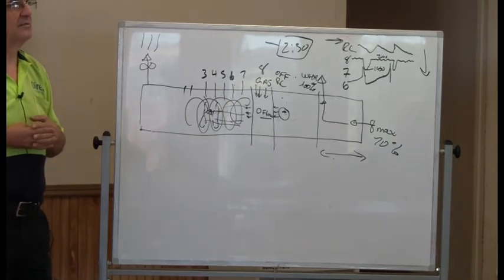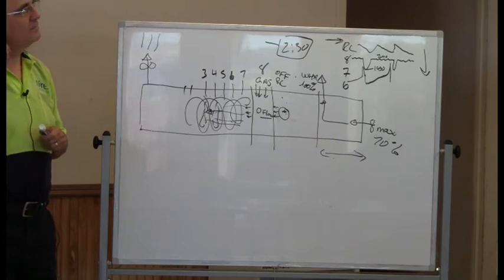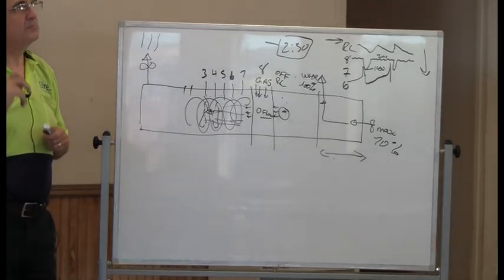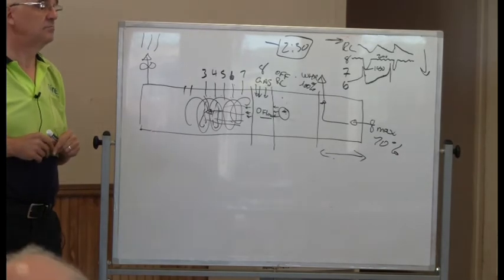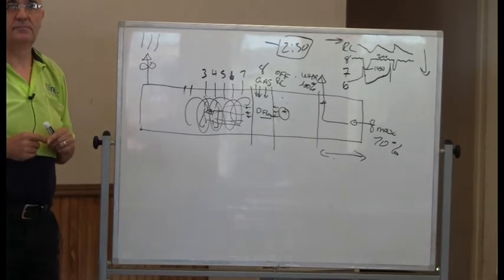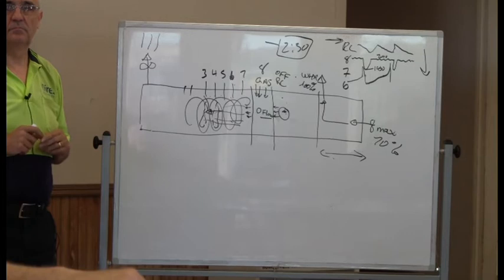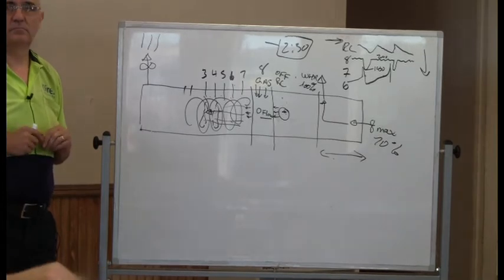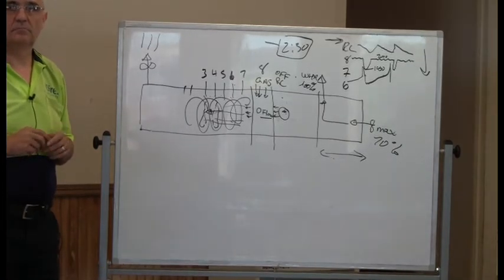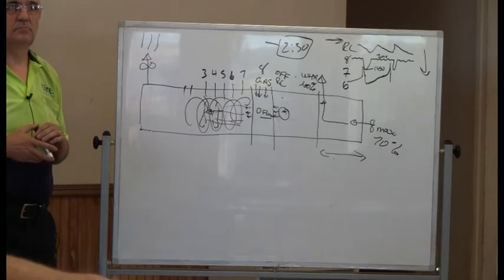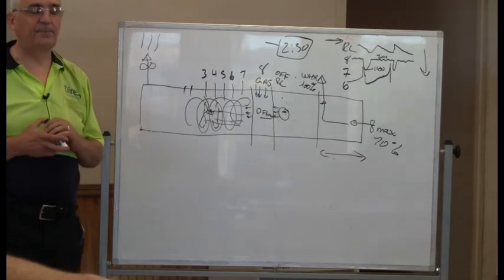Yeah, well, basically, I guess in my mind if we're tanking a temperature, we're not seeing that flare, right? Yeah. And just leave the burner group on. Yes. Set yourself up to where it's either 5 or 4, probably somewhere in either 4 or 3. You won't be going back much further than that, because at that point it's probably going to burn off. But with your exhaust, you want it to pull just enough to keep the smoke moving a little bit out of the exhaust.